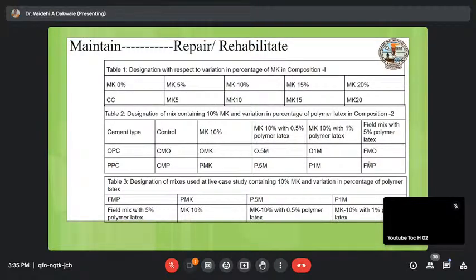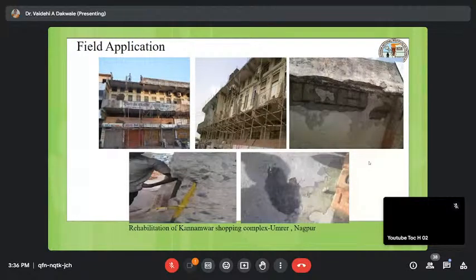There was a repairing mortar which was used by the industry. So we cut down the polymer latex the industry was using, 7%, to 0.5% of polymer latex. We added some 10% of metakaolin by weight of the cement and used that whole mix on the repairing. We got this composition patented recently. So these are the case studies which we did for that particular